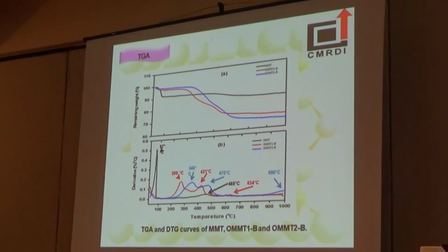Thermogravimetric analysis showed that the decomposition of the clay takes place in only 2 steps. The first step is at 67, which is due to the dehydration of the water, and the second step was at 465 due to the removal of the structural hydroxyl group.